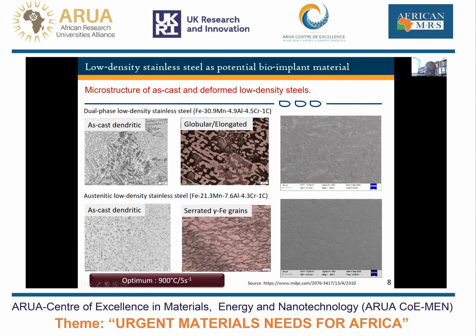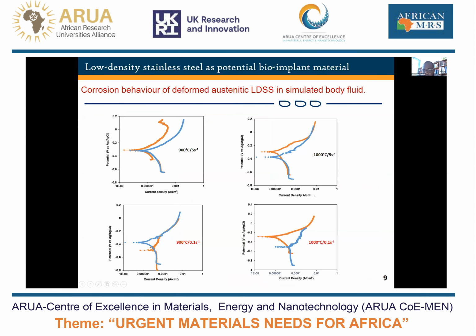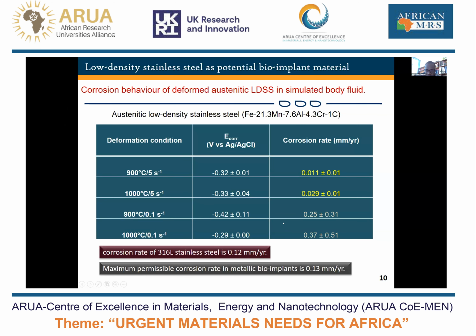And what we see is that through thermomechanical processing, we were able to change the microstructure. But does this affect the corrosion results? You can see that in this case, when we use this particular parameter, we were able to find results that are nearly reproducible. And in calculating the corrosion rate and E corr as well, we see that for this same parameter, it's quite close and the standard deviation is quite low. When we use a strain rate that is much slower, the results are not necessarily reproducible, which shows that there are some variations in the microstructure and we need to optimize the thermomechanical processing parameters.